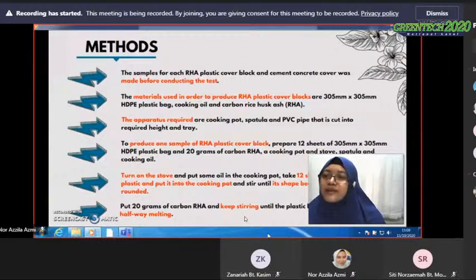Okay, the third one is methods. The samples for each RHA plastic cover block and cement concrete cover were made before conducting the test. The materials used to produce RHA plastic cover blocks are 305 mm by 305 mm HDPE plastic bags, cooking oil and carbon rice husk ash. The apparatus required are a cooking pot, spatula, and PVC pipe that is cut into required height, and a tray. To produce one sample of RHA plastic cover blocks, prepare 12 sheets of HDPE plastic bag and 20 grams of carbon RHA.